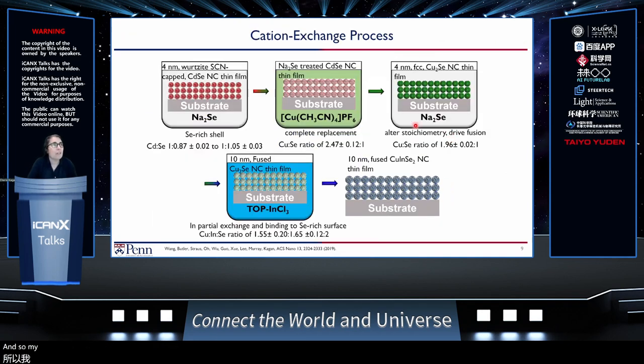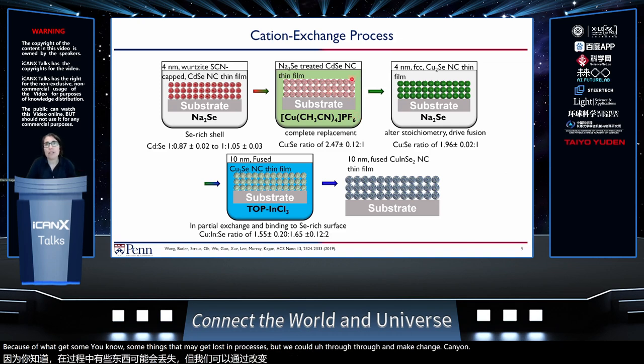And so my student Han started with the cadmium selenide sample and developed a process where he would change the surface chemistry of the materials. He'd bring them close together. He'd swap and introduce selenium on the surface. That helped. Then we would introduce and swap the cadmium for copper. And so we could make copper selenide materials. Some of these steps are to control stoichiometry, because some things may get lost in the processes, but we could go through and change cadmium selenide to copper selenide.